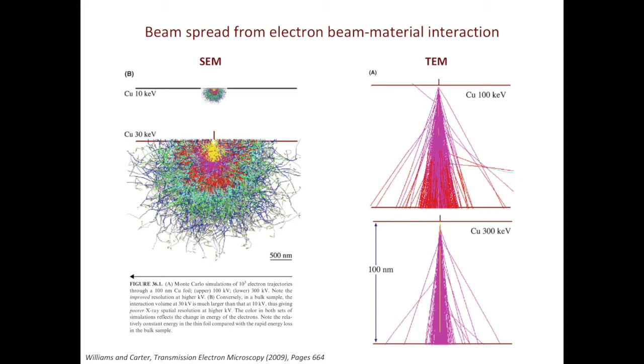However, you will gain resolution by reducing the wavelength of the electron beam. So there is a fine balance between the resolution determined by the interaction volume and the resolution determined by the wavelength of the beam.